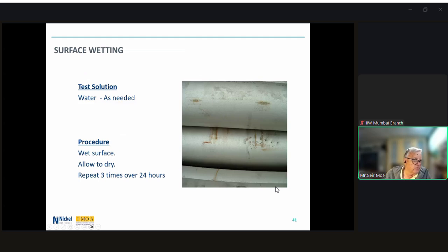And briefly discussing surface wetting. Surface wetting is fairly straightforward. You wet the stainless steel surface and wait. Any surface iron contamination will eventually rust. This is sometimes seen on fabrications when they are shipped from the fabricator to the customer. During fabrication, the surface of the equipment becomes contaminated in the fabrication shop, but since the fabrication takes place undercover, the iron contamination possibly doesn't rust. Then the equipment is transported to the customer and it rains during transport, and the iron contamination rusts by the time the equipment reaches the customer or while it's sitting in the customer's yard. So here, it's a fairly simple process. Wet the surface, allow it to dry, and repeat a number of times over a 24-hour period.